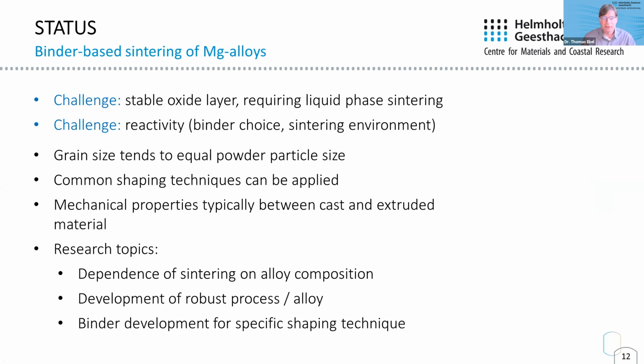But in the end, when I'd like to sum up a little bit the actual status now, I would say, first of all, if you sinter magnesium, it always means you have two challenges. One is really the stable oxide layer. So you have to find a way to break this layer up, because otherwise the powder will usually not sinter. The second challenge is, of course, magnesium is very reactive. So you have to avoid any additional oxygen and if possible also carbon and so on.